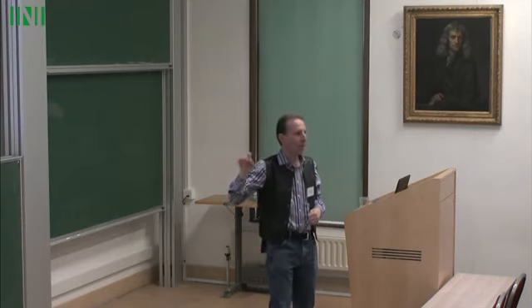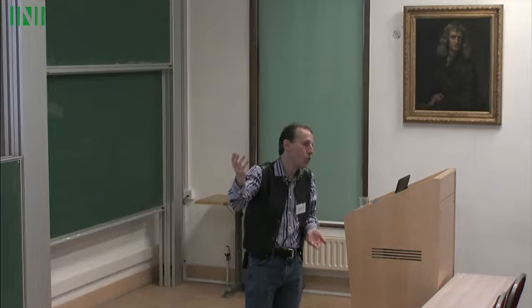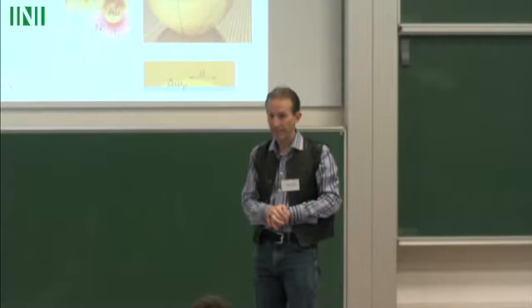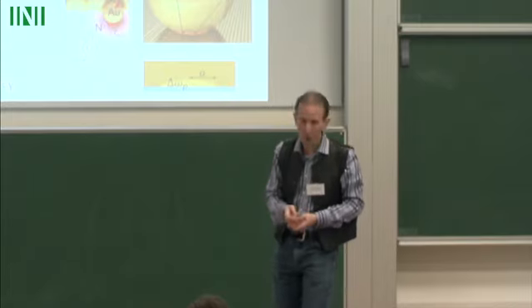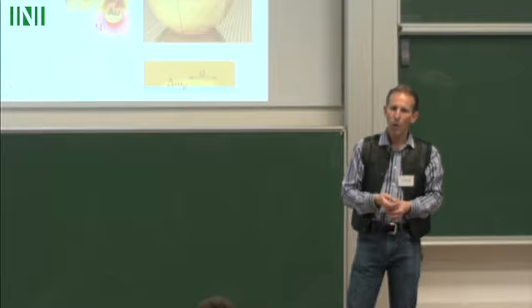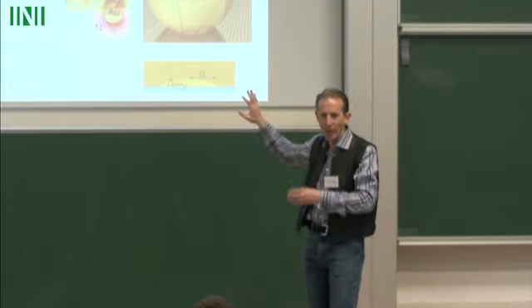So in your pico cavity thing, is there a connection to SERS? I mean, can you get the effect also with... Yeah, so this is all working as surface-enhanced Raman scattering. The fact that we get very strong fields inside these gaps amplifies enormously the Raman scattering, and that's why we can see 50 molecules or even down to one molecule or one bond. As we learn how to localize light tighter and tighter, we actually realize you can look at one bond in real time in ambient conditions and do chemistry. So you could use silver as well? You could use silver. Silver works just fine, but of course silver oxidizes. So we mainly stick to gold because we've got enough problems.